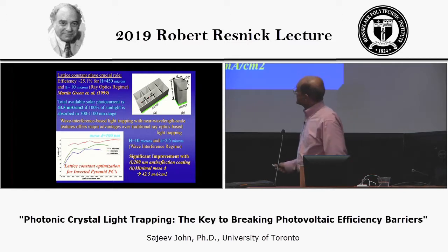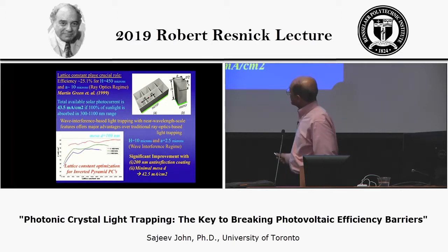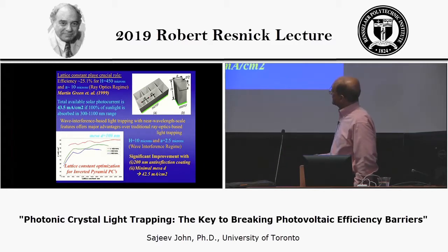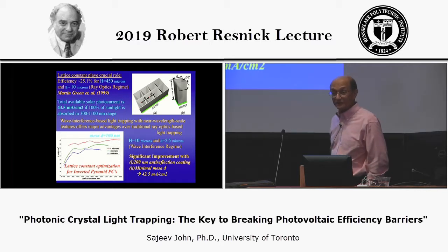Now here you see some simulations for much thinner structures where the height, the thickness of the structure is considered to be 3 microns, 5, or 10 microns. And what we look at is what is the maximum achievable photocurrent density as a function of wavelength, and there's typically some optimum depending on the thickness. For the 10 micron case, the optimum is a lattice constant, this parameter A, of about 2.5 microns.